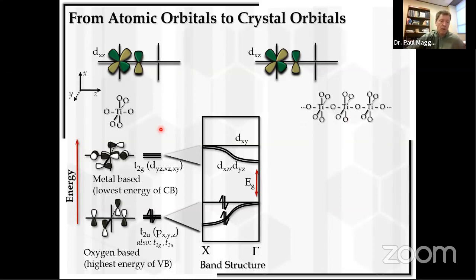So I have the simple molecular orbital diagram of the frontier energy levels for a TiO6 octahedron here. And the band gap, or in this case, the HOMO-LUMO splitting, is determined by the non-bonding oxygen p orbitals here in the t2u and then the pi star unfilled levels of the d orbitals on titanium here, the d_yz, d_xz, and d_xy. And that splitting determines its gap, okay?